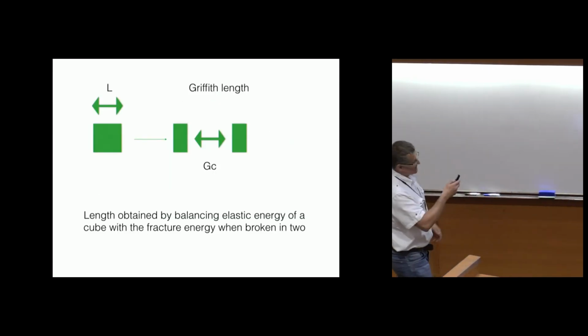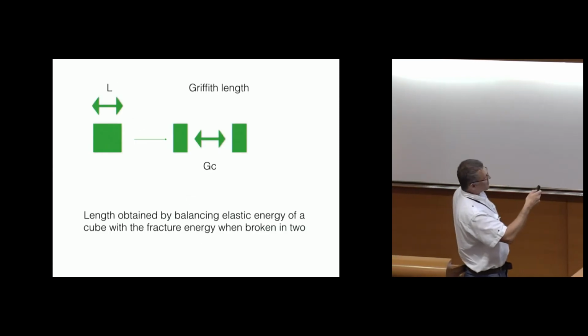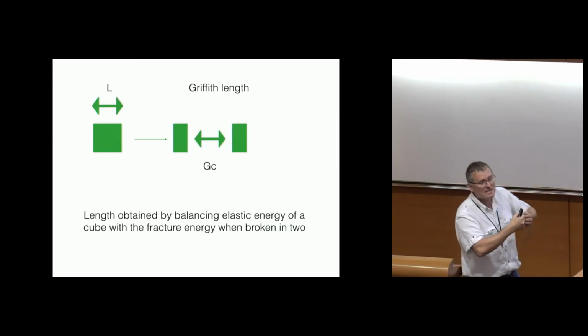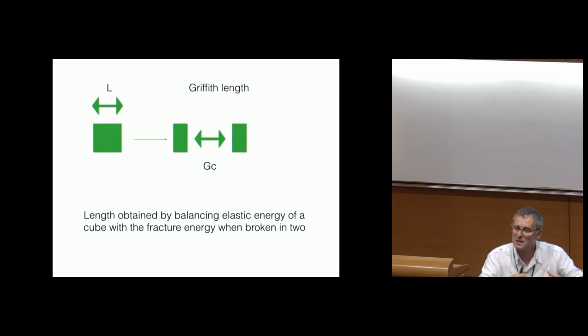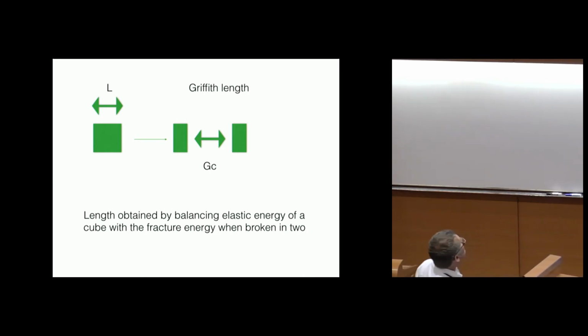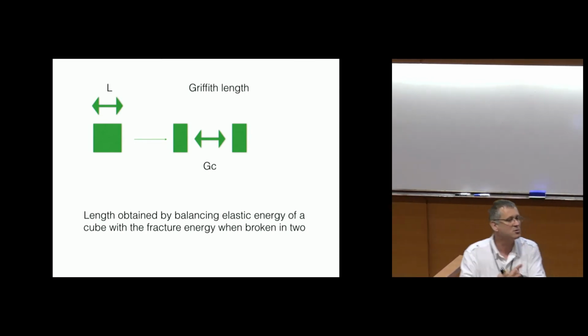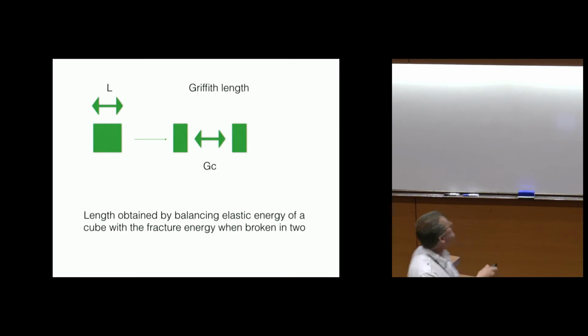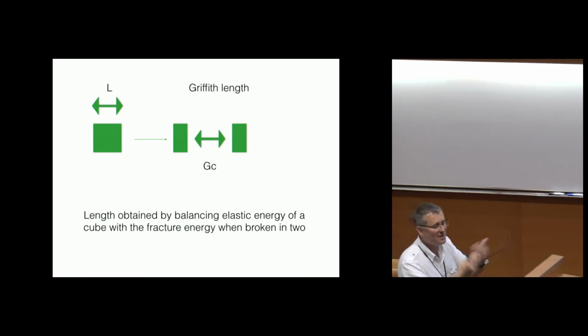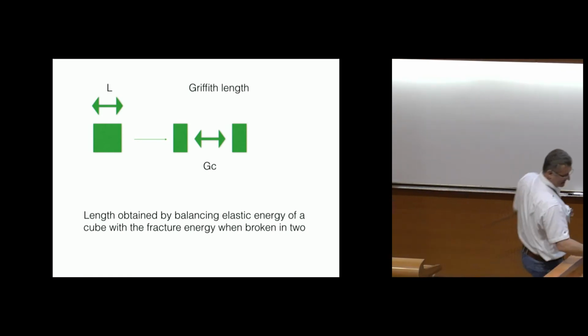That means you can compare the energy that is due to elastic deformation in your system to the energy that you would need to create the cracks. So you know that creating the cracks means creating a surface, and so it costs you some energy by surface, while the elastic energy is in the volume. So you see that immediately you have a length scale that is appearing.